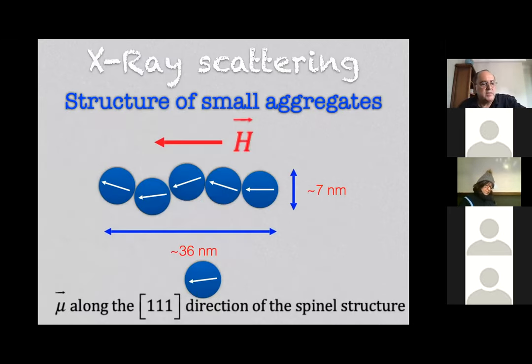And we made X-ray scattering also to understand what's going on when we put these magnetic fields in the sample. Let me see the time here. Oh my God, let me finish. The field that we put in our sample is a field that makes this type of linear aggregates, not bunches. We don't have this type of big aggregates formed, and we have basically 7 nanometers in that direction and about 5 particles.